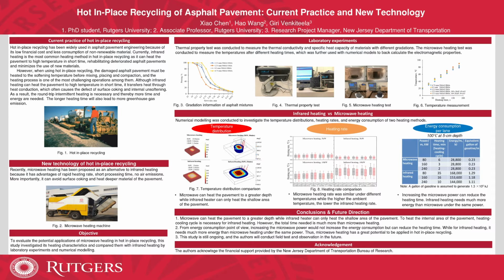And additionally, infrared heating rate was lower than microwave heating rate under 5 kilowatts power, as we can see, but it becomes the opposite side when the power was 10 kilowatts. It also shows that increasing the power can increase the infrared heating rate more effectively than microwave.